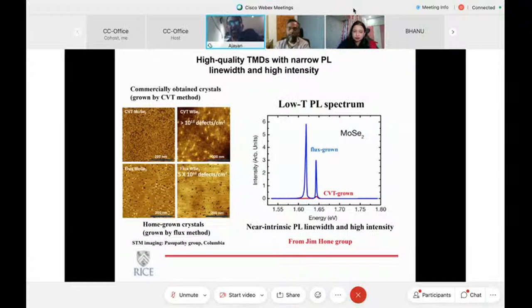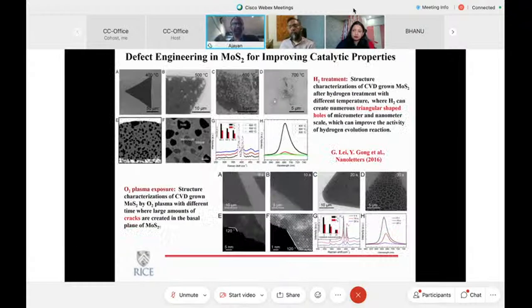Sharper peak if the material. So there's certainly a correlation between electronic structure and defect densities. And again, it has not been so easy to control the kind of defects that appear because the growth itself is kind of complicated and high temperature. It's pretty hard to control defects. I think there is a window in which you could actually work, but still, that would be an area for the future to optimize.